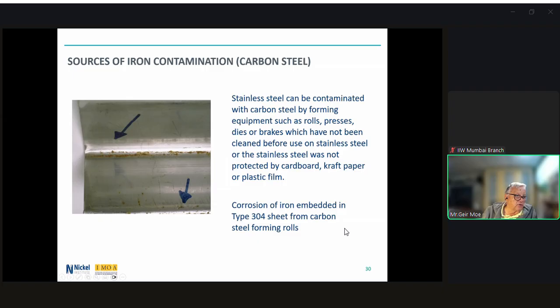Forming equipment can transfer carbon steel particles to stainless steel formed with that equipment if the equipment has not been cleaned prior to its use on stainless steel, or if the stainless steel has not been protected by an insulator such as cardboard, kraft paper, or plastic film. And in this photo, we can see corrosion of iron that has been embedded in a sheet of 304 from carbon steel forming rolls.